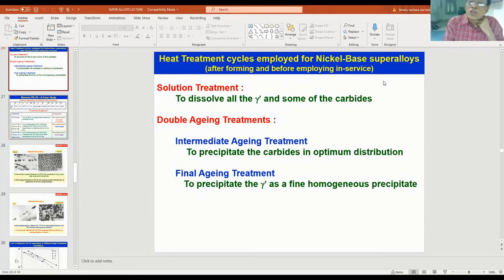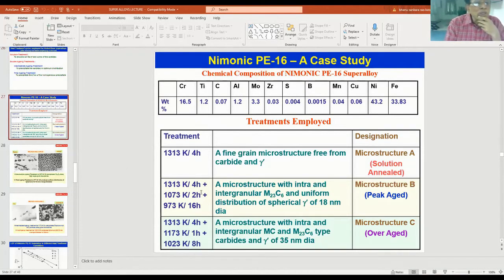So nickel-based superalloys are generally given the solution treatment followed by double or triple aging treatments. Triple aging means that in between, an aging treatment can be given in order to precipitate your gamma prime strengthening phase in different sizes, one coarse precipitate, one fine precipitate, and like that. So I will give you an example here.